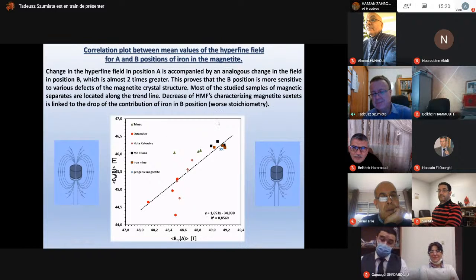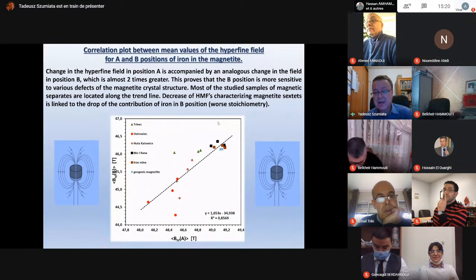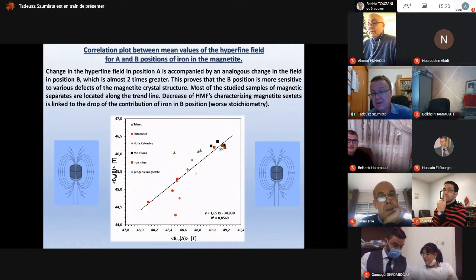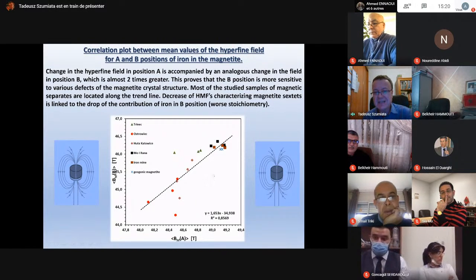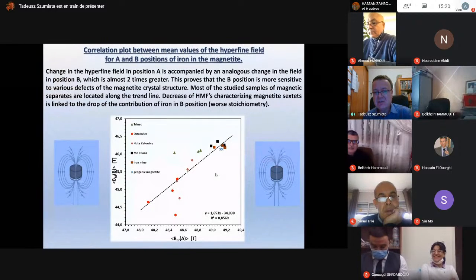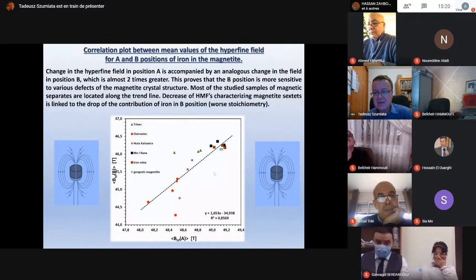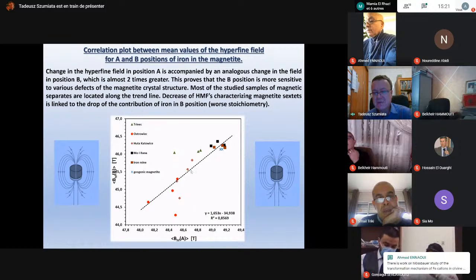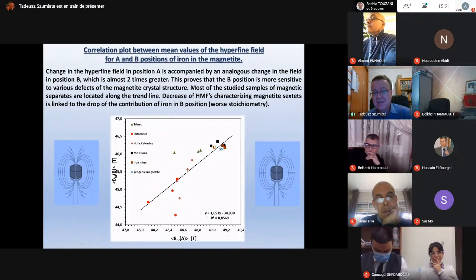In this plot, you see the values of hyperfine magnetic fields, which are parameters of Mössbauer spectra, the values both for this A and B position in magnetite, and we can say that there is some kind of linear correlation between these values, not perfect, but it is. So one can conclude that if we have some defects inside the magnetite, they change the whole electronic structure of magnetite. And a very trivial observation: if we have samples of natural, very stoichiometric magnetite, we can see that the values of both hyperfine magnetic fields are the highest.